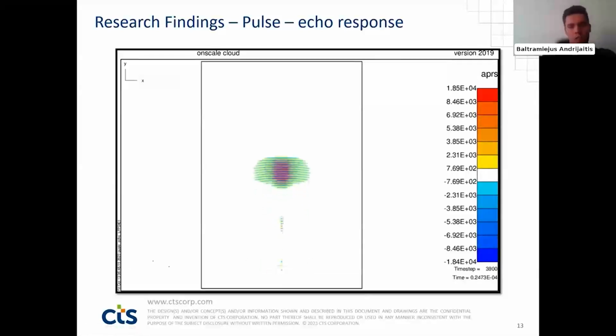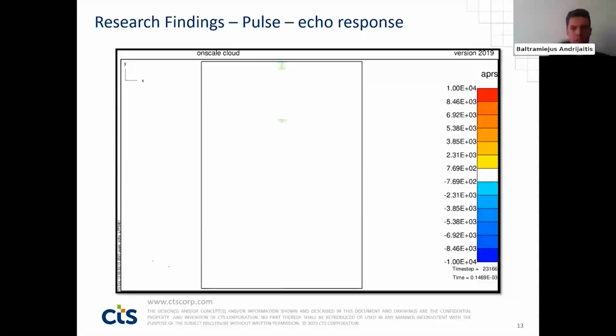This is the video pulse echo simulation. We can see high frequency 20 pulses that were excited in the ceramics, traveling in the water, hitting the mirror, and traveling back where the echo signal is read. So here, talking about what is important to perform a good pulse echo finite analysis: it is important that a high acoustical impedance material should be used for the mirror. In this case, it was stainless steel. And another point, the distance between the sample and the mirror should be set exactly as in the real case. Otherwise, the signal would not represent the real case in general.